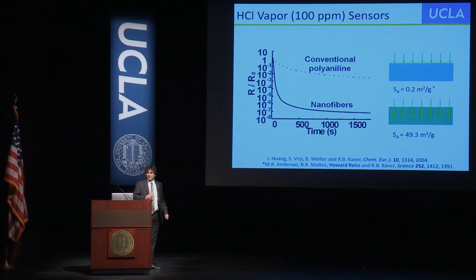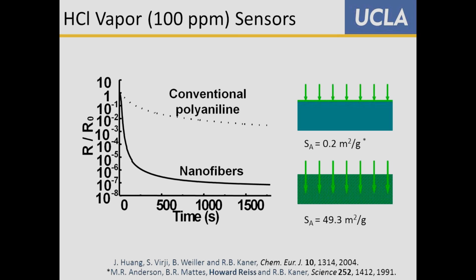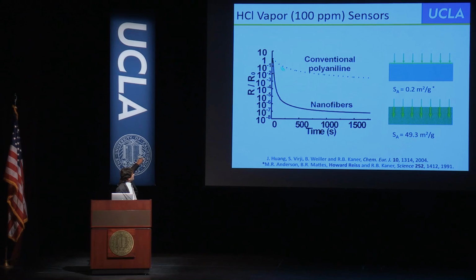Okay, getting back to sensors. So Bruce and I looked at the sensor activity, and here's the change in resistance on a log scale versus time. Here's the conventional material. It sees an acid, and the resistance drops. Here's the nanomaterial. It drops 6 orders of magnitude greater.